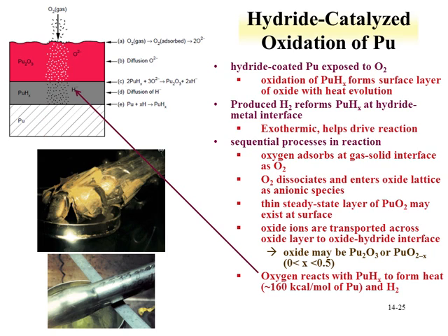Now, why this is important is that for storage of plutonium metal, you want to prevent any sort of oxidation from occurring because it goes from a very dense material to a lighter material. That means you have swelling, as an example here, of two storage containers that contain plutonium metal. Upon this oxidation reaction, the material converted from the metal to the oxide and the hydride, swelling the package and in one case bursting the package.